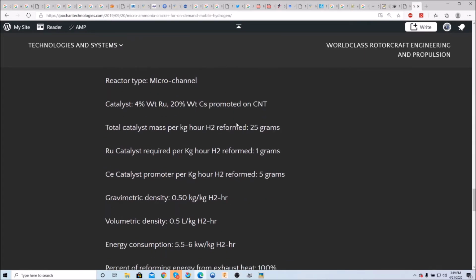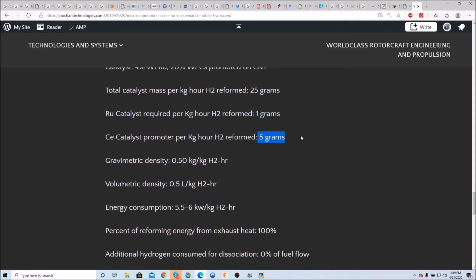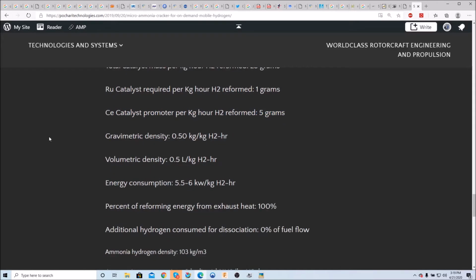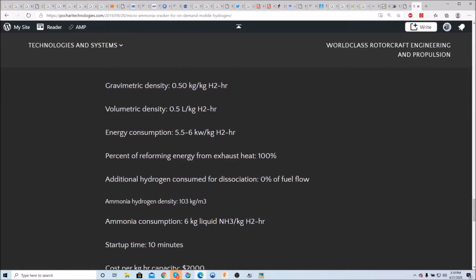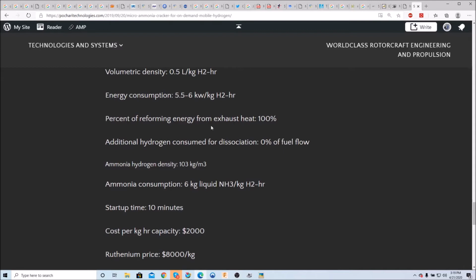Okay, so ruthenium required for 1 kilogram of hydrogen formed: 1 gram. Okay, and cesium 5 grams. So gravimetric density, the cracker only weighs half a kilogram per kilogram of hydrogen produced per hour. The density is only half a liter per kilogram of hydrogen produced per hour, and the energy consumption is probably 6 kilowatt hours per kilogram, although that's going to vary a lot depending on the temperature. And from the exhaust gas, we can get 100% of the energy.